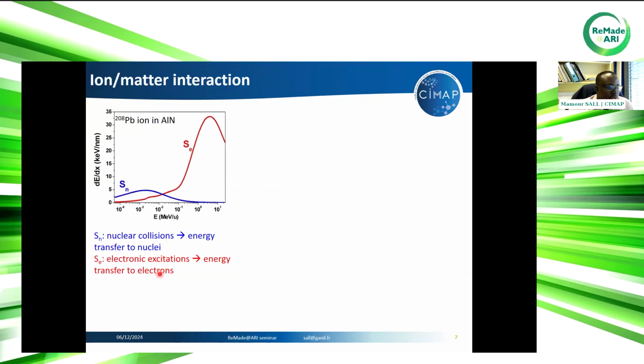And the other one is what we call electronic excitation. In this case, the projectile will transfer its energy to the electrons. So in this case, the defect creation, the material modification, will be an indirect process because the energy is transferred to the electrons before going to the lattice. This figure is an example of the evolution of these two parameters. Sn is for nuclear collision, so direct collision between projectile and nuclei, and Se is the electronic excitation. These two parameters are represented for lead ion in aluminum nitride as a function of the ion energy. What we can see here is that at low energy, the dominant mechanism is nuclear collision, while at high energy, electronic excitation becomes dominant.